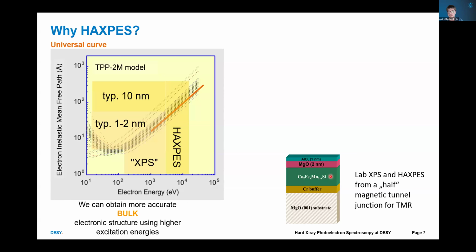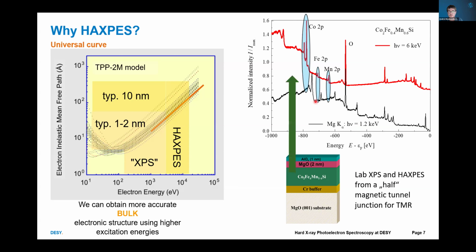And this is an example which compares laboratory XPS and hard X-ray photoelectron spectroscopy spectra from a kind of half TMR junction, which is cobalt, iron, manganese, silicon, evaporated on an MgO substrate, and then you have a kind of buffer layer, MgO, and a capping layer. If you use the laboratory source, you see only signal coming from the capping layer. And using 6 keV excitation, we get signal from the interface and from the bulk of the cobalt, iron, manganese, silicon film, which is buried underneath the capping and buffer layer.